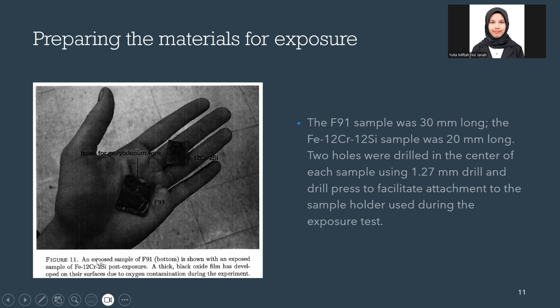You can see from figure 11, this sample is F91, and this sample is Fe-12Cr-12Si. This figure shows an F91 sample, and the bottom shows an exposed sample of Fe-12Cr-12Si post exposure. I think a black oxide film developed on their surface due to oxygen contamination during the experiment.